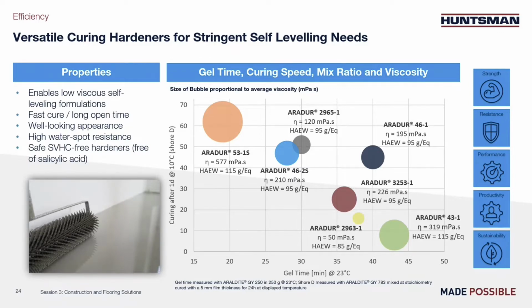Over the years, many accelerators used in those hardeners became substances of very high concern. And we have always been very proactive to anticipate those changes. Also, you can see the -1 or the -2, which means we either removed phenol, bisphenol A, nonylphenol, and more recently, the salicylic acid. On the graph, we have mapped 7 of those hardeners. The x-axis gives an idea of the gel time at room temperature, while the y-axis gives an idea of the hardness development at 10 degrees. The size of the bubble is proportional to the viscosity as usual, here at least.